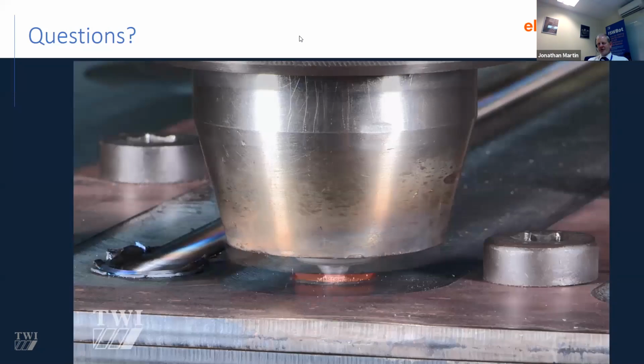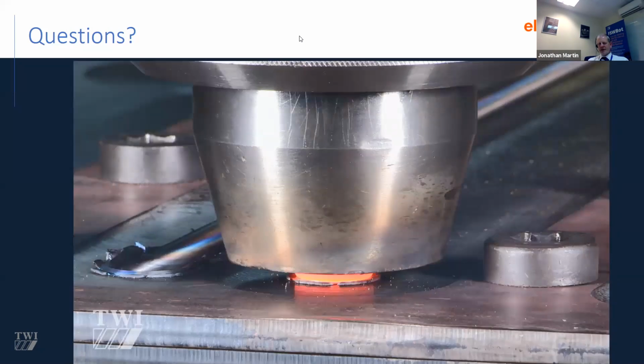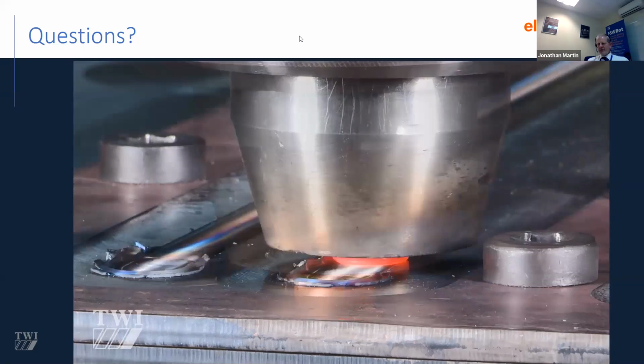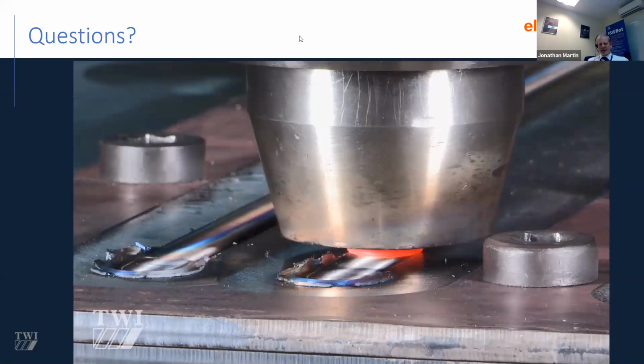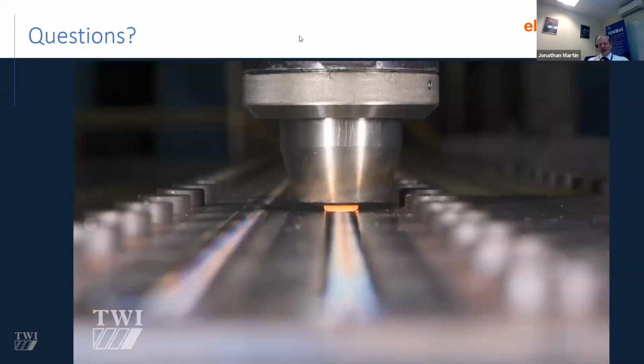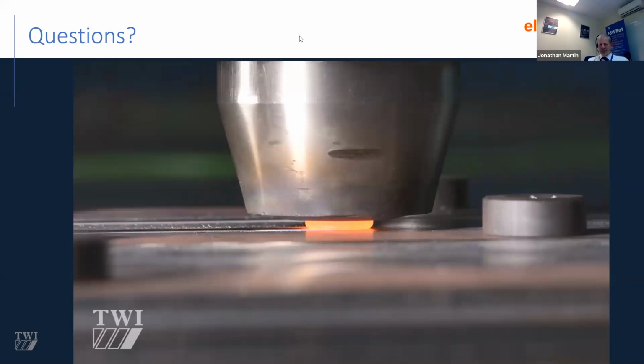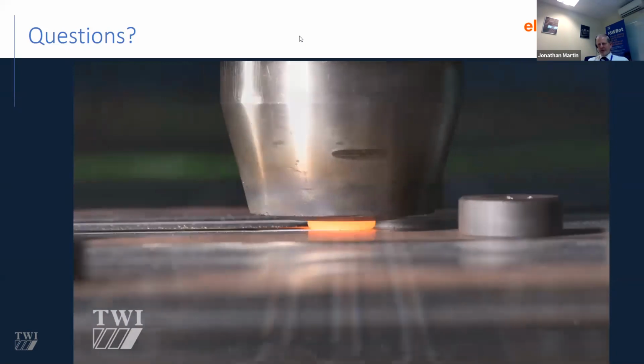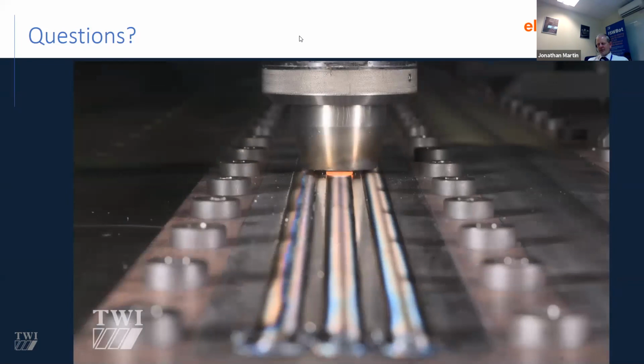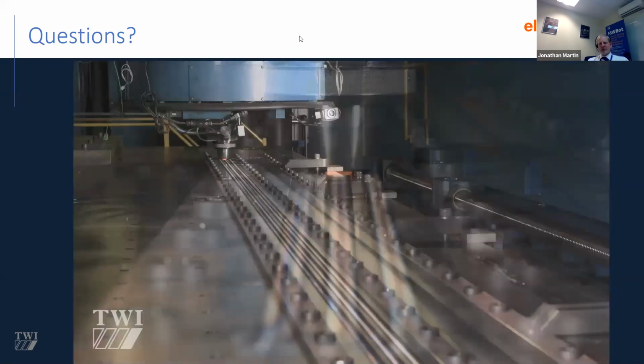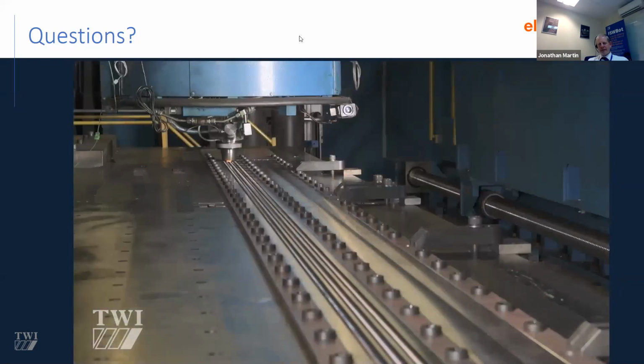So the form of the weld that we're producing in steel will be subject to the same sort of flaws that you would see in aluminium. So this is perhaps voids, lack of penetration. The type of defects that we potentially would need to assess and test for will be very similar, and therefore the techniques that have been developed for friction stir welding of aluminium, we would anticipate would read across.